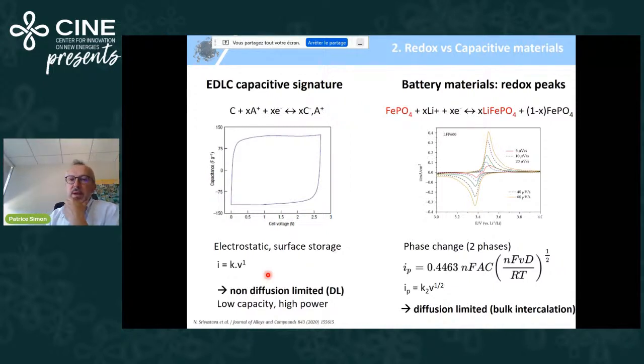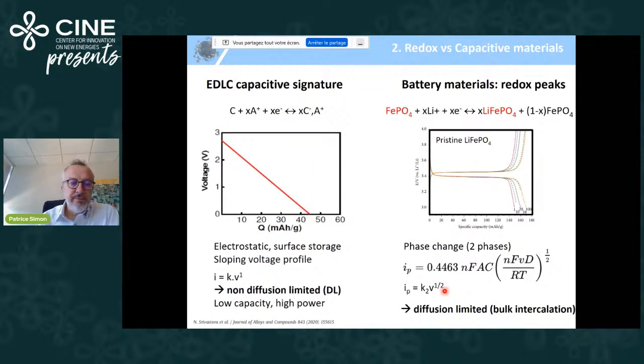Low capacity, high power. If you move to redox materials like battery materials, this is an example of the LiFePO4/FePO4 redox couple, so this is LFP. Here, this is oxidation of LFP, removal of lithium, and intercalation of lithium into FP. You can see sharp redox peaks, and a peak current decrease because of diffusion limitation. This peak current on both sides is proportional, thanks to the Randles-Sevcik equation, to the square root of the scan rate. So this is a typical signature of diffusion-limited processes. And this is the galvanostatic profile, not cyclic voltammetry, just for your knowledge: a sloping profile for capacitive, and a plateau for a redox two-phase material.